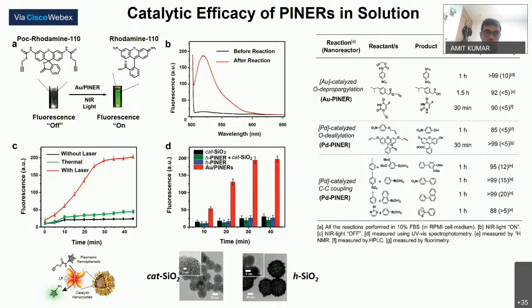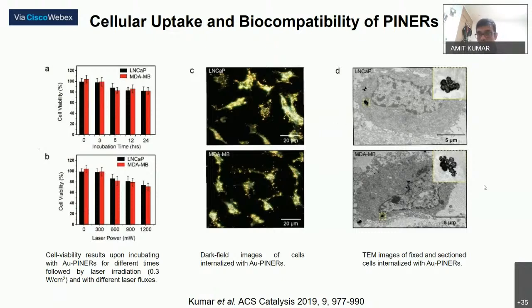To treat these nanoreactors with cells, that was the ultimate goal, to see whether these nanoreactors can enter inside the cells. So we fed different cells with the nanoparticles at different times. And we saw that 3 hours is enough to internalize a sufficient amount of nanoreactors into the cell. Then we irradiated with an NIR laser to test whether it affects cell viability. A 3 hour incubation time was optimum for almost 100% cell survival. And we also optimized the laser power. 300 milliwatt per centimeter square was the optimum laser power for such a reaction.